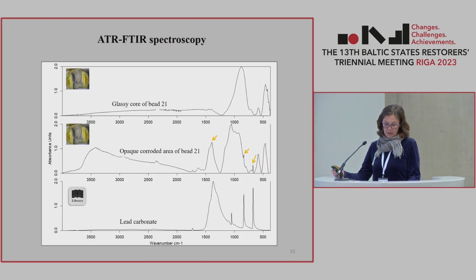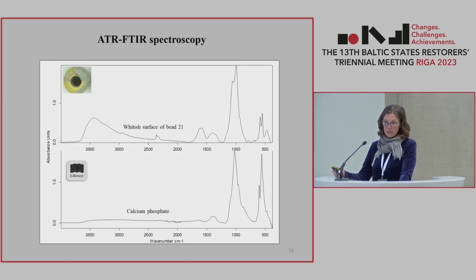After research, some uncertainty remained. What is the whitish surface of the bead, like a crust? In the slide, you can see presented spectroscopy results of composition analysis of beads in different areas. Yellow marked bands, which were identified in the opaque bright yellow zone, coincide well with the comparative data of lead carbonate. We state that lead carbonate formed in the lead silicate glass through a corrosion process, while the opaque bead on the whitish surface is linked to calcium phosphate, which developed due to long interaction between the glass materials and the archaeological environment.